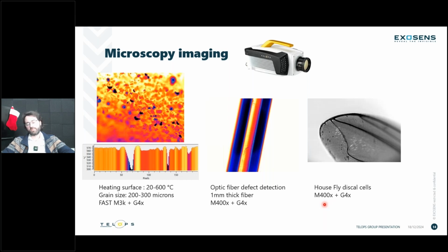Now for microscopy imaging, some really interesting data that was taken in 2024. Some people were interested in a heating surface, but at a microscopic level. So these are very small grains, around 200, 300 microns maybe. So it's a very dark surface, closer to a black body in terms of surface. But you can see there's non-uniformity in those grains. So with that microscopy lens, and we're talking about a G4X, so you're multiplying the pixel pitch by 4 to have your pixel resolution, spatial resolution.